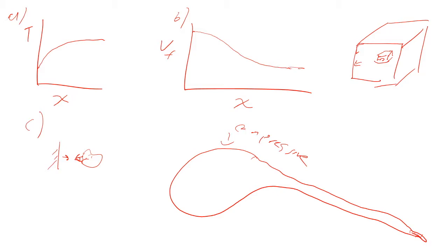How fast does that crack travel? Basically the speed of sound, right? The shear wave velocity in the material, right? So you've got this crack that's propagating at the speed of sound into the really high... the really high, right? So now I've got huge tensile stresses here that want to relieve themselves on this internal, right? This is all massively tensile. This is massively compressive, right? So this then radiates out tons and tons and tons of cracks.